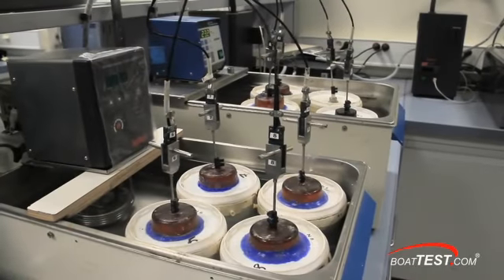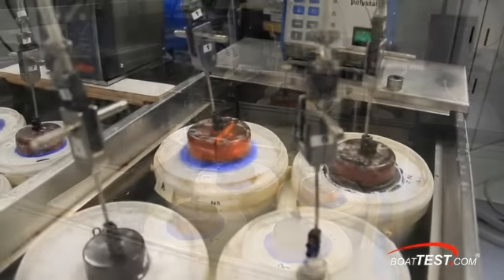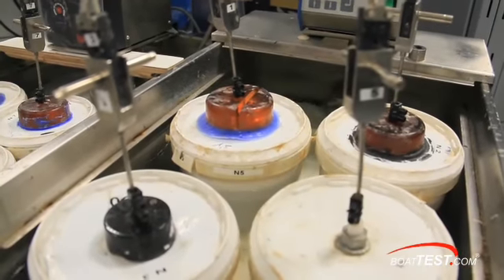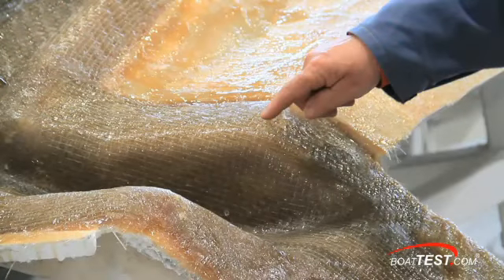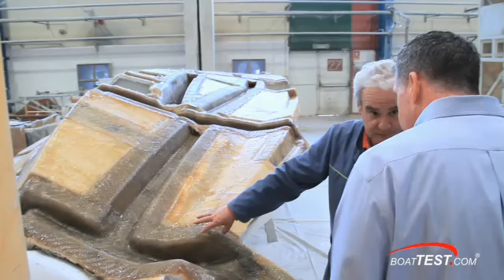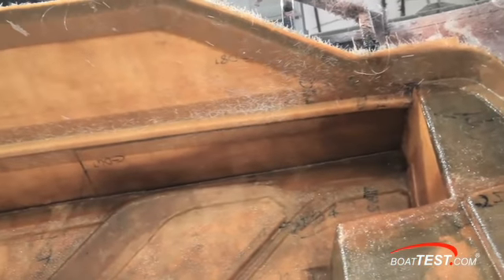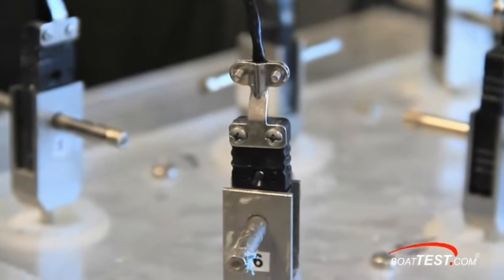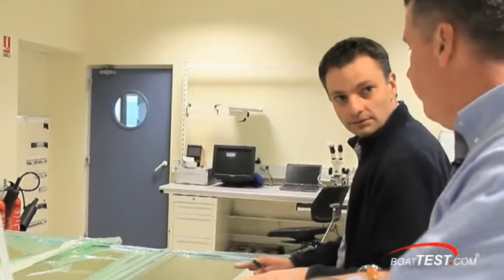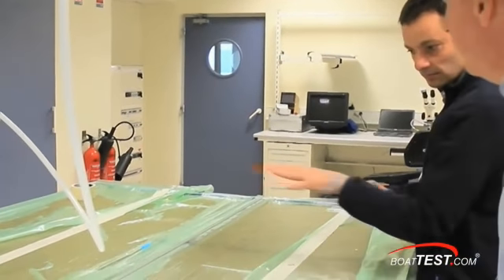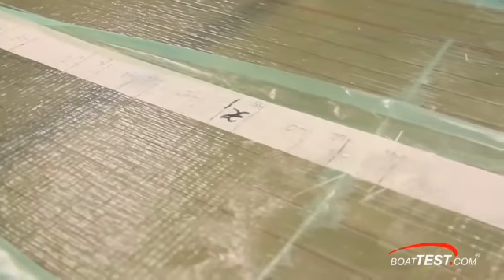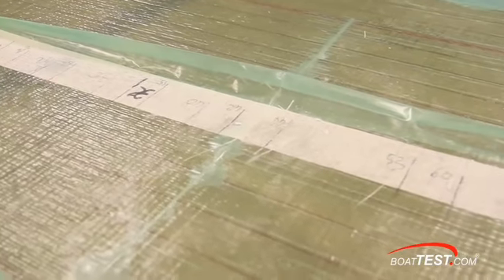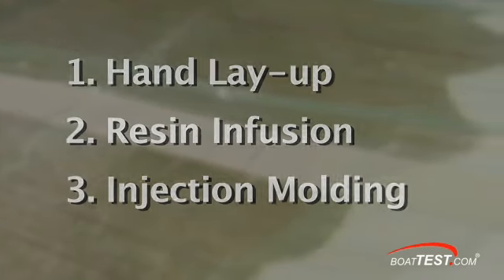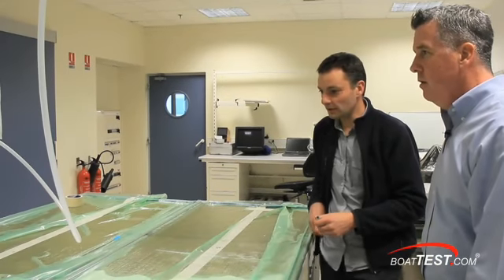Here we see reactivity testing of the resin, which measures how much time it takes for the resin to cure from liquid to a solid state. This test is conducted to make sure Beneteau optimizes the time it allows for the resin to set up in each of its processes. The probes are thermometers, which are attached to a computer. Here we see testing of the resin during the vacuum infusion process. This test measures the flow rate and several other parameters. Since Beneteau uses the resin in 3 different processes, tests for each is ongoing to ensure quality standards are maintained.